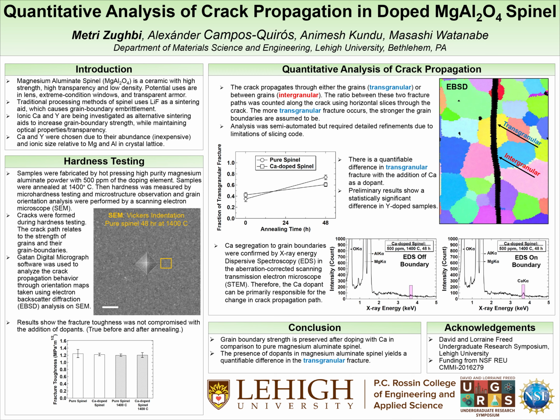This is because if there's more transgranular fracture, which means there's more through the grain, then the grain boundaries are being strengthened by the dopants. This analysis is done by using the software to take horizontal slices through each of these pictures, and there are about 7 pictures per crack, and comparing the color of the grain on either side of the crack, which is that big black line going down the middle. And if the colors are the same, we say the crack is going through the grain.